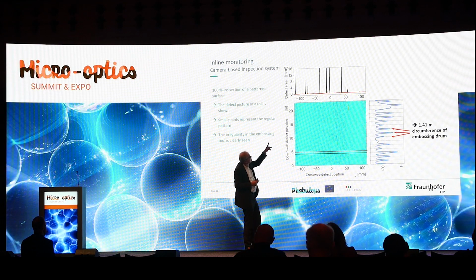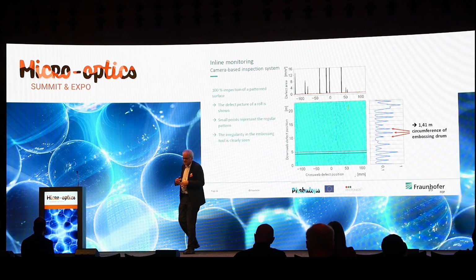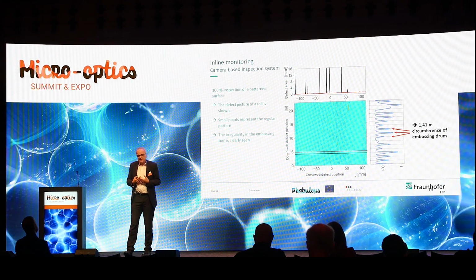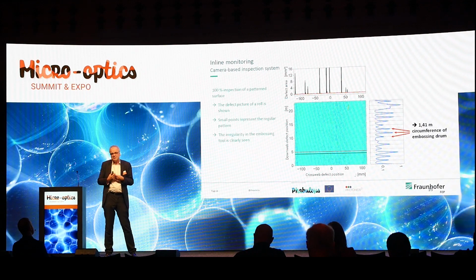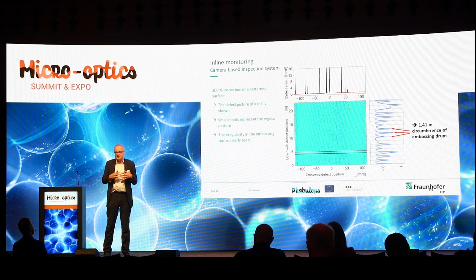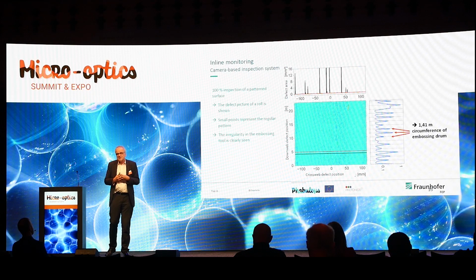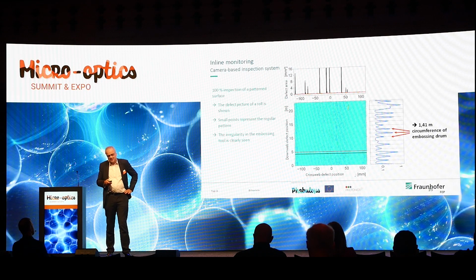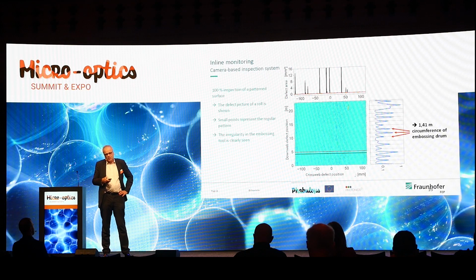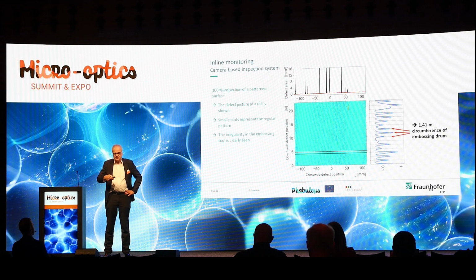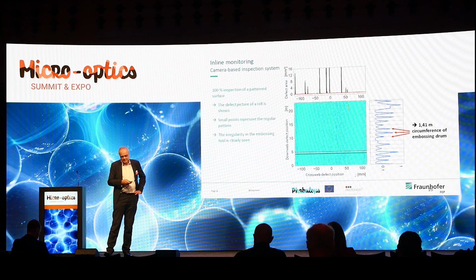And in the downward direction, you also have some peaks, and these peaks then really tell you something about irregularities which come from the coating process. In this case, it was the slot die coating process. There was something not exactly adjusted with the deposition thickness at these points, and that was clearly detected by this device. And it was a very valuable and successful tool, which we could transfer from the defect recognition on a flat film to a defect recognition on a pattern film.